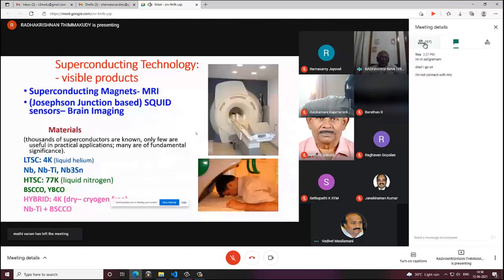High temperature superconductors can superconduct at 77 Kelvin, liquid nitrogen. Candidate materials are BISCO, bismuth strontium calcium copper oxide, and YBCO, yttrium barium copper oxide. You have now a new candidate material, MgB2. They are still to be harnessed in a very big way as technical superconductors, but a lot of work is going on. If they do, the need for low temperature liquid helium refrigeration may not be necessary. On the other hand, low temperature refrigerators are also getting highly developed. Nowadays, where liquid helium is necessary, you can use a 4 Kelvin refrigerator that can operate non-stop with power.